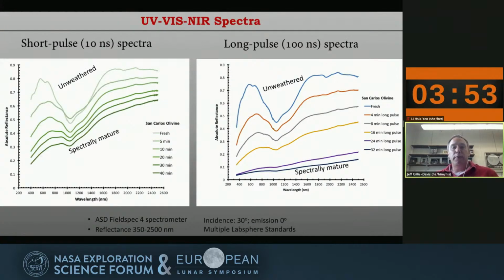So as I mentioned before, on the left are the spectra of San Carlos olivine that we have laser weathered with the short pulse. You can see at the very top, you have a nice 1 micron absorption, and then after about 40 minutes, it becomes what we call spectrally mature. It doesn't change much, even if we add more laser radiation. You can see the spectrum is red. The 1 micron feature is still somewhat present, and it has darkened.